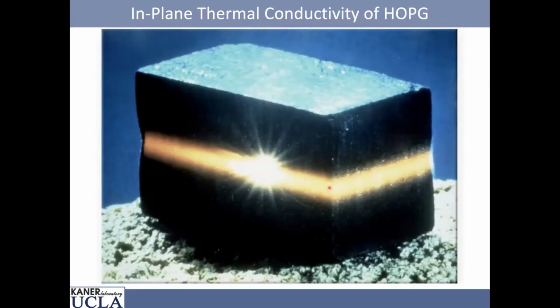And in graphite, the sp2 carbon is all bonded in plane. Heat is also conducted by carriers of electricity, in this case, electrons, and those are all due to the pi overlap, which is also in the same plane. So if you hit it with the laser here, and you were to touch over here, you'd burn yourself, but the top is still cold. So we're looking at heat conduction in 2 dimensions. And this is the only picture I've ever seen of a molecular scale property in real 3-dimensional space. So it's kind of an interesting look at low dimensions.